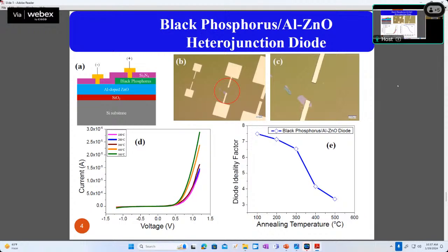Our group fabricated a simple device called a PN junction diode, where the black phosphorus works as the p-type layer of the PN junction, and aluminum-doped zinc oxide is used as the n-type layer. This whole thing is kept above silicon oxide. You can see the silicon oxide substrate was there, and on top of that it is fabricated. Using a fabrication technique called lithography, we made two electrodes, and we measured the current-voltage characteristics at different temperatures.